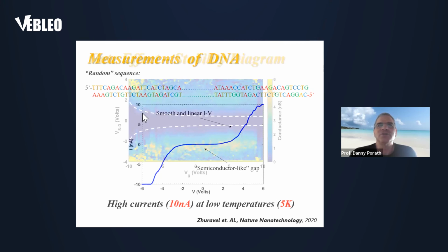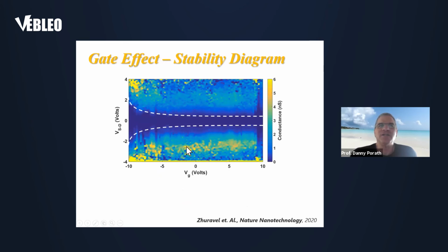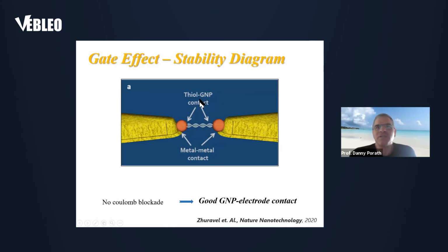Then we went forward and we looked at the gate effect, and we can see that it is quite smooth, different than the diamond structure that we saw before. And that indicates that the contact between the dimer nanoparticles and the electrode is very good, as we wanted to have, and we don't have Coulomb blockade effects. So this is the scheme that I mentioned before. The good contact is here and between the molecule and the nanoparticles.